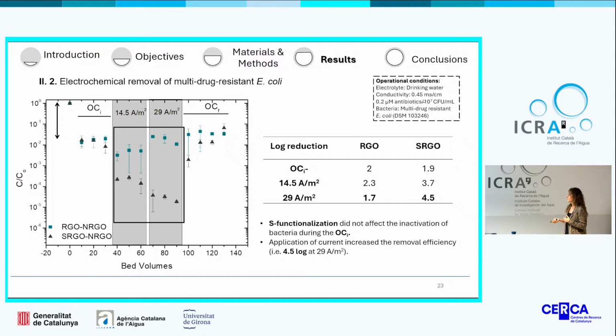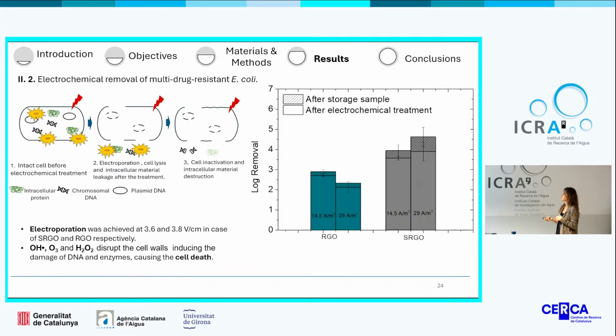When the current was applied, we could observe two different behaviors. In the case of sulfur-reduced graphene oxide, an increase of the removal was observed, achieving 4.5 log inactivation of E. coli. However, on the contrary, in reduced graphene oxide, an increase of current led to a detrimental impact on the inactivation of bacteria, which is probably a consequence of secondary reactions such as oxygen bubbles, which block the active sites of the electrodes and directly affect the effectiveness of our treatment.